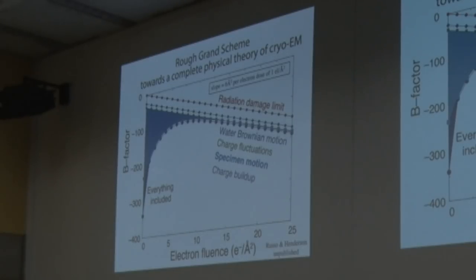And then these are factors in the imaging procedure, in the physics of the interaction between the beam and the specimen that degrade the image. So one of them is that the water, the thin film of Dubochet plunge frozen ice, the water itself gets damaged. And the water molecules, H dot, OH dot, OH minus, H plus and so on, they move around and they reassociate, but they've moved. So there's what we call water pseudo-Brownian motion induced by the beam. And we don't mind about the water molecules. That's a nice, even background. But it pushes the molecules around. But fortunately, we've measured it now, and it's not a killer factor, but it reduces this B factor slightly because of Brownian motion.